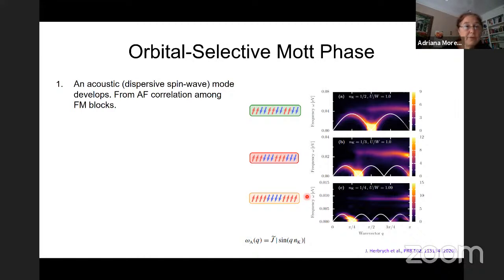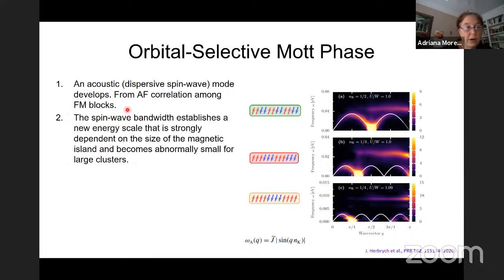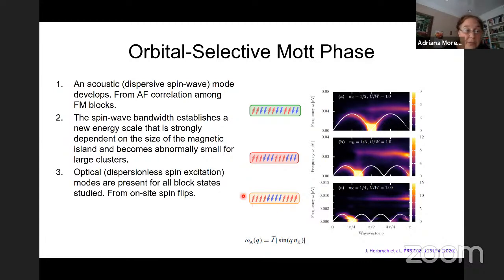The spin wave bandwidth establishes a new energy scale that is strongly dependent on the size of the magnetic island and becomes abnormally small for large clusters. You see here we have the 4 size clusters and this amplitude gets reduced. And the optical, mostly dispersionless spin excitation modes are present for all block states, and we believe that they come from on-site spin flips.